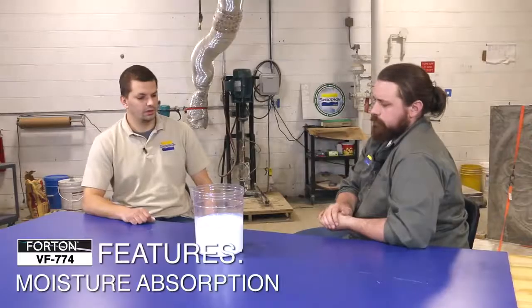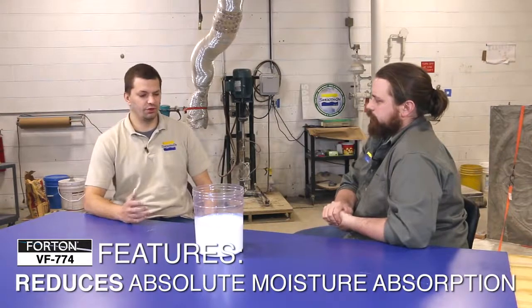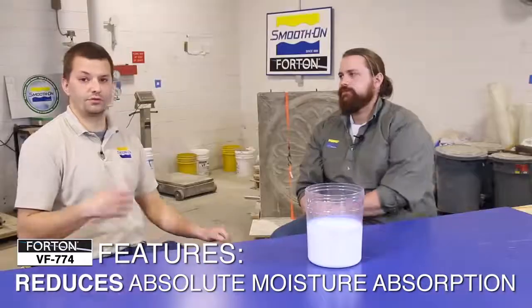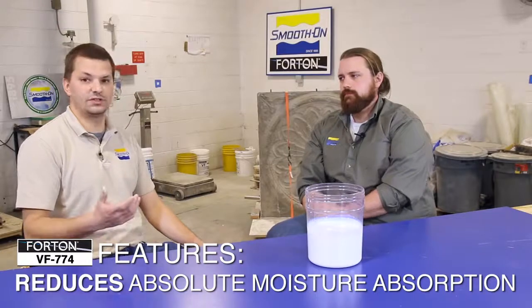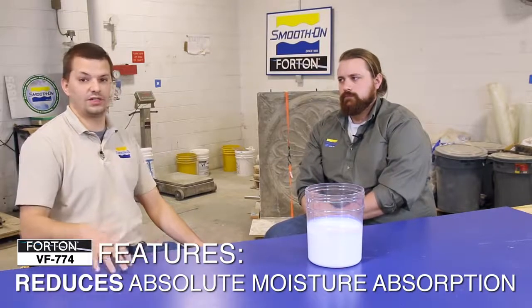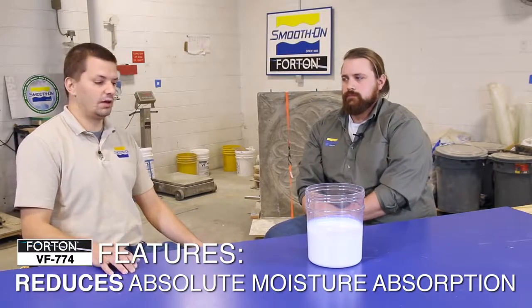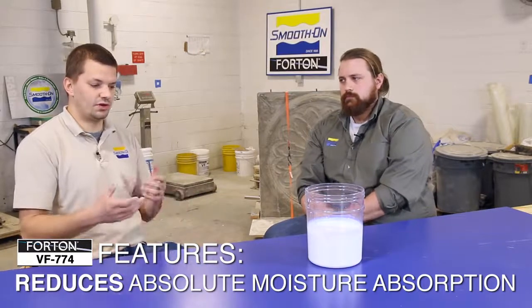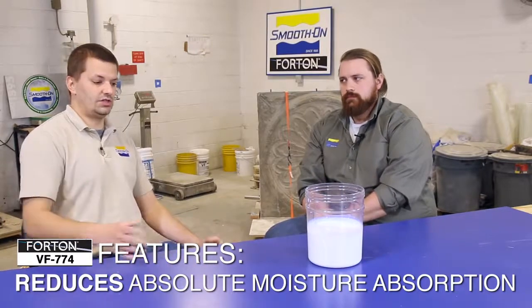Like moisture absorption. Yeah, moisture absorption is something that most people don't think about, but when you're really going for the freeze-thaw cycles or even efflorescence, it comes down to how the water gets into the concrete to begin with. With the polymer in there, it seals all the porosity and makes the overall water absorption less. Therefore, you get increased freeze-thaw cycles, as well as less efflorescence or salt migration through concrete, causing the white milky powder substance on the outside of the concrete. It really cuts down on a lot of that.